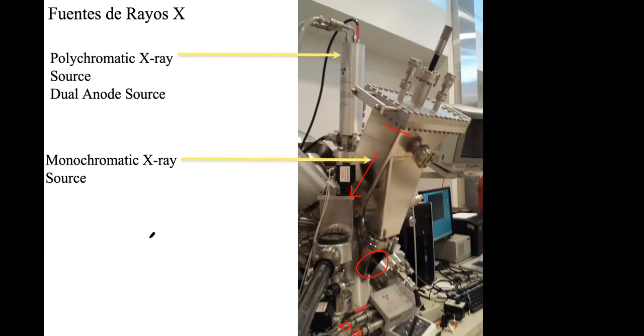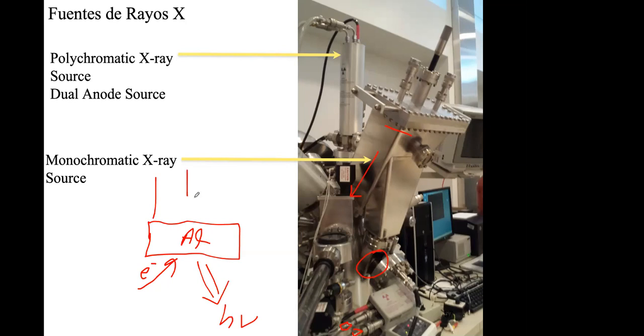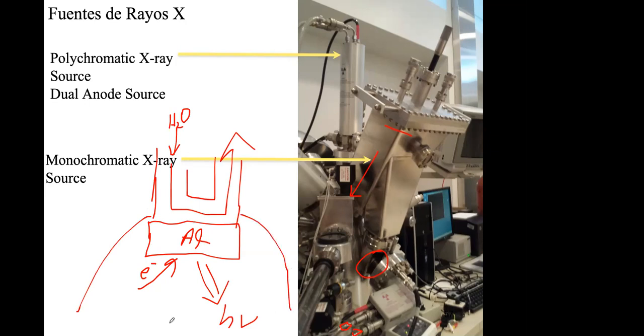The other thing that happens here, let's say this is aluminum, and here you're hitting this with electrons, and it's giving away photons, and back here you have your cooling system. They try to use deionized water, you cool the water, and it goes in this direction. Remember, this is inside the chamber. This is in ultra high vacuum, about 10 to the minus 10 torr, and this is at one atmosphere. So if this melts, water will go in.